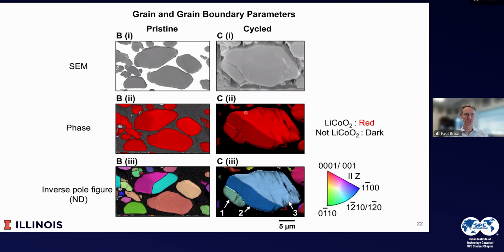And so here we look, this is just a classic powder, the SEM when it's pristine, and after cycling, you can see the cracking. When we do a phase map, it is pure. This is what's expected. These are commercial lithium cobalt oxide powders. And when we do an inverse pole figure, what we can see is, for example, the crack here occurred between, even though this was a single particle, it had 2 grains, and one grain cycled differently than the other, and that led to cracking along the interface.